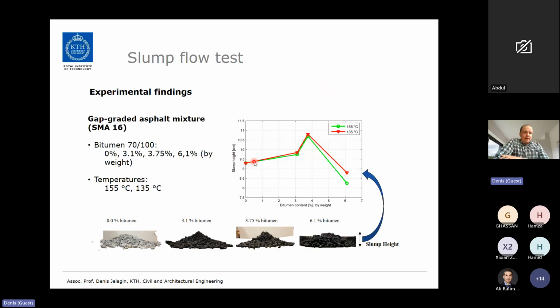So first thing we noticed early on that in contrast to concrete, we cannot look at slump spread because asphalt tends to deform differently. Some of the stones will disconnect and roll very far. So we discovered that way more representative measure of asphalt flowability is actually to look at slump height instead of slump spread. So here we looked at different binder content from 0%, so pure unbound material, 3.1, and all the way to 6.1% at two different temperatures, 155 and 135 degrees Celsius.